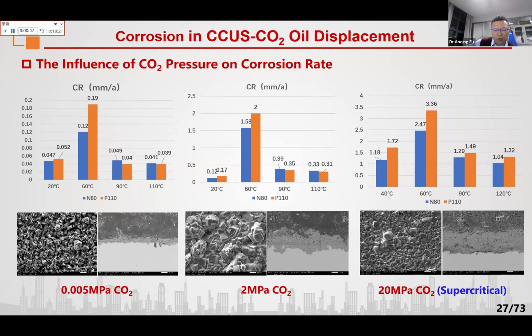Here we also did some metallurgical analysis, that means the microstructure of the corrosion products. Actually, we found that the corrosion mechanism does not change, no matter whether CO2 is in the normal or supercritical state. As for why the corrosion rate is very high, I think the main reason is that the CO2 partial pressure is pretty high.